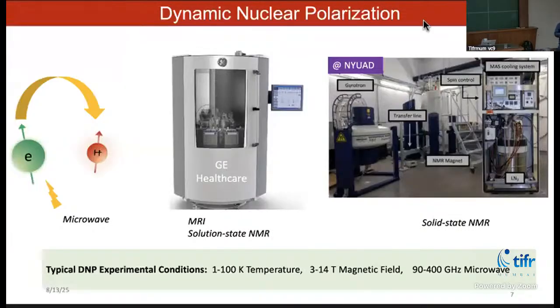So if someone is doing DNP MRI, the DNP is done at 1 Kelvin, and whatever you are hyperpolarizing could be a metabolite that is quickly melted and injected for in vivo scanning. Or if someone is doing solution state NMR, again, you do the DNP, hyperpolarize the sample at 1 Kelvin, quickly melt the sample, and then do the solution state NMR. For MRI, yes, people have hyperpolarized pyruvate, a few other metabolites, and injected into humans for in vivo imaging. The human does not have to be at 1 Kelvin, just the metabolite. After injecting it, it basically thermalizes with the human body. Yes, exactly, the process retains the hyperpolarization.